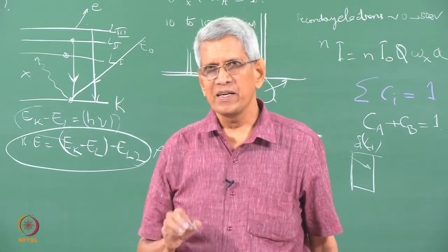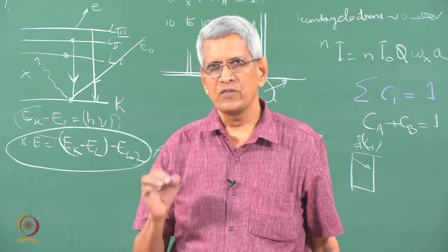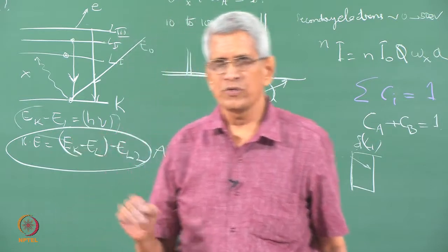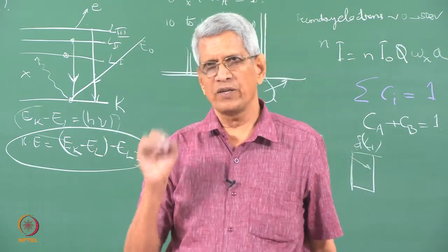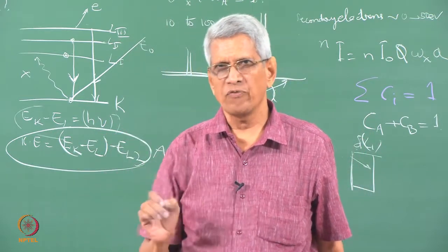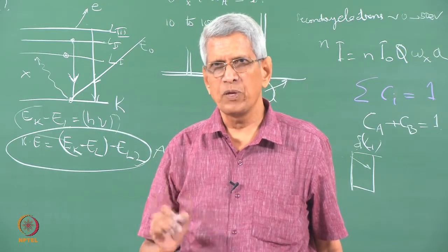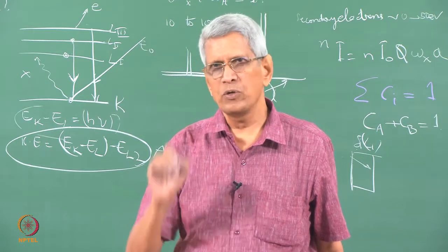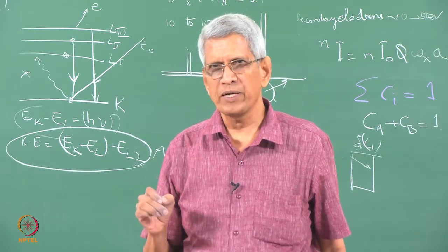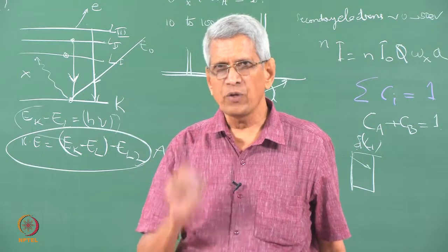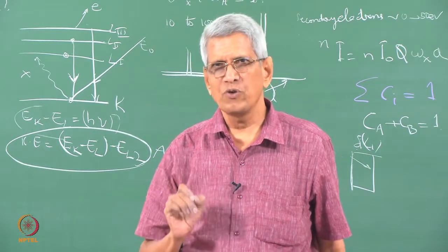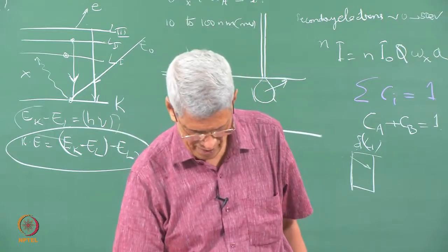Another point is that for high Z elements we can use this to find out the composition with some confidence, because for low Z elements below 1 keV, absorption is going to be quite high. We may be able to obtain a peak corresponding to a particular element, but finding the composition accurately is not a trivial task. That requires a lot of extra care.